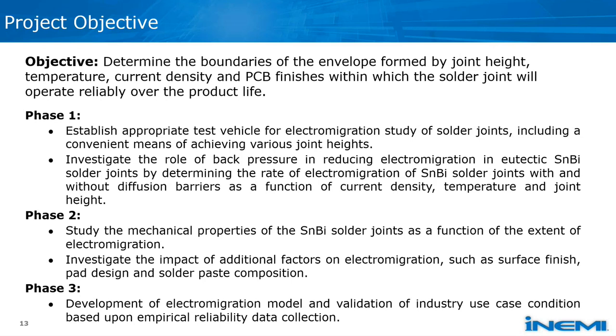As PJ described, there is a back stress effect during electromigration. This back stress appears to diminish the electromigration within the solder joint. This phase will therefore investigate the role of the back stress in reducing electromigration as a function of current density, temperature, and joint thickness. This will be done both with and without the nickel diffusion barrier at the solder joint to termination land interfaces.